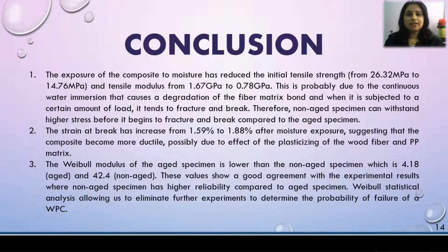In a nutshell, there are three conclusions that can be made from all this analysis. Firstly, the exposure of the composite to moisture has reduced the initial tensile strength from 26.32 megapascal to 14.76 megapascal and tensile modulus from 1.67 gigapascal to 0.78 gigapascal. This is probably due to the continuous water immersion that causes a degradation of the fiber matrix bond, and when it is subjected to a certain amount of load, it tends to fracture and break. Therefore, the non-aged specimen can withstand higher stress before it begins to fracture and break compared to the aged specimen.